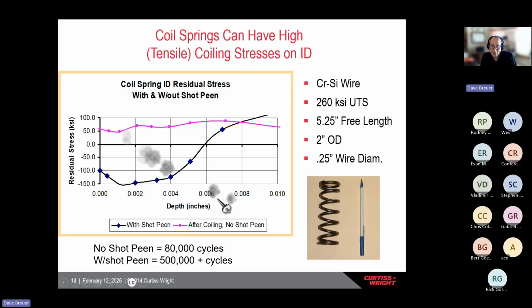Let's say the spring has a cyclic tensile stress of 100 KSI. You actually have to add on 50 to 70 when you add the residual plus the applied for the total stress. Now when you shot peen, this is going to disappear because the shot peen is going to convert - this residual stress gets converted into this. So imagine this pink curve disappearing. With shot peening, in this example, you have 100 to 150 KSI of compressive stress at the surface.